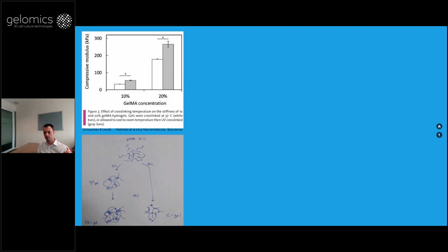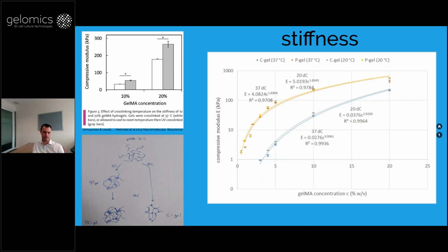The first GelMA paper said it loses its ability to form a gel if you make it into GelMA, which is mostly true for gelatin type B, but GelMA made from gelatin type A still does gel a lot more. And it leads to an enormous increase in stiffness. We see up to 40 times increased stiffness at the same concentration. But if you look at it differently, you can make a gel and create the same stiffness with much less GelMA. So it's another parameter, and it's also good to keep in mind when you're making a gel: if you allow it to gel physically, you will get a much higher stiffness.